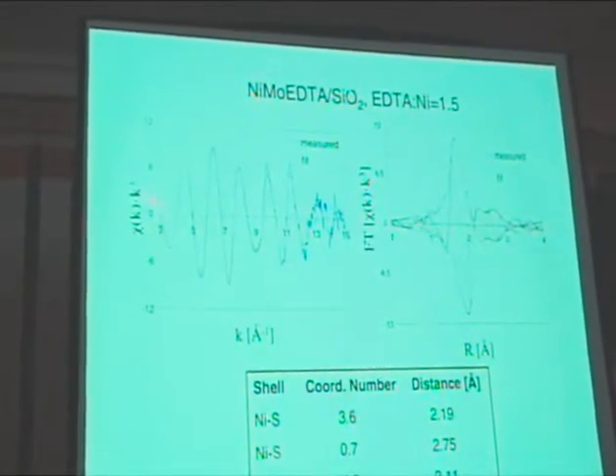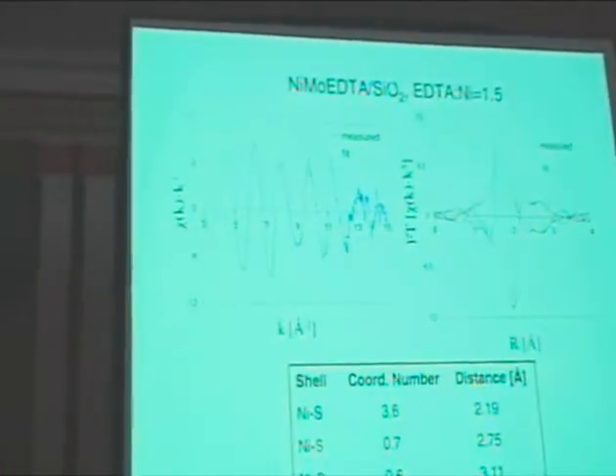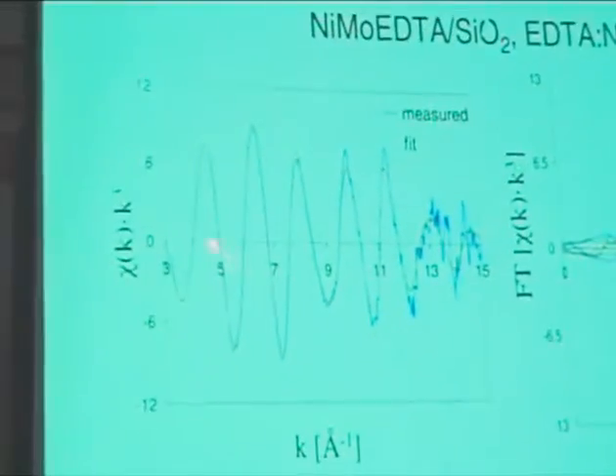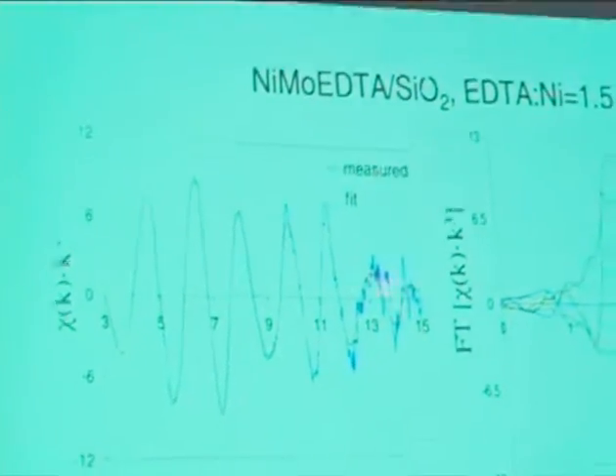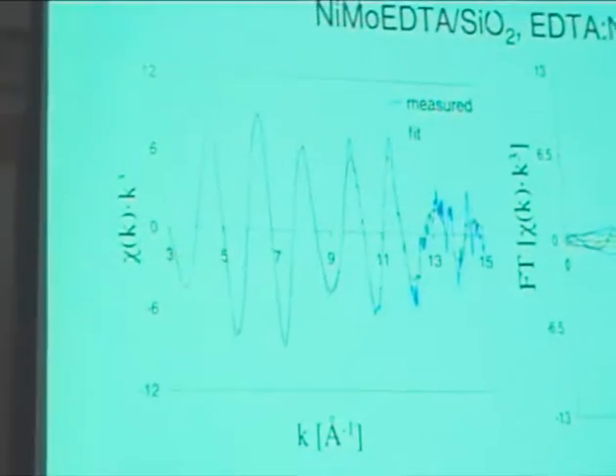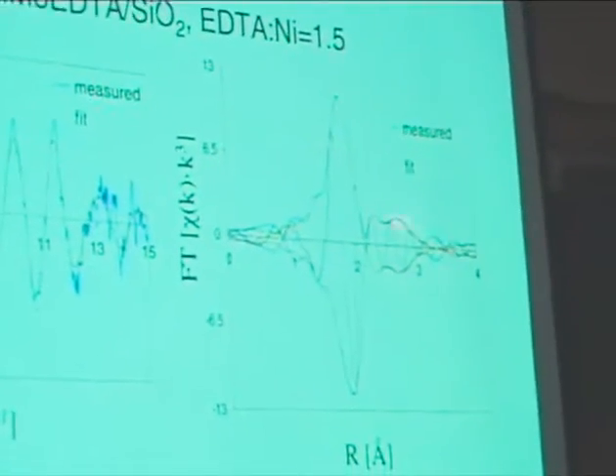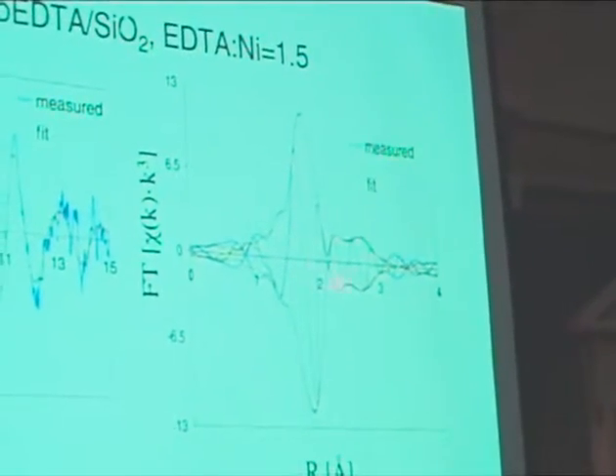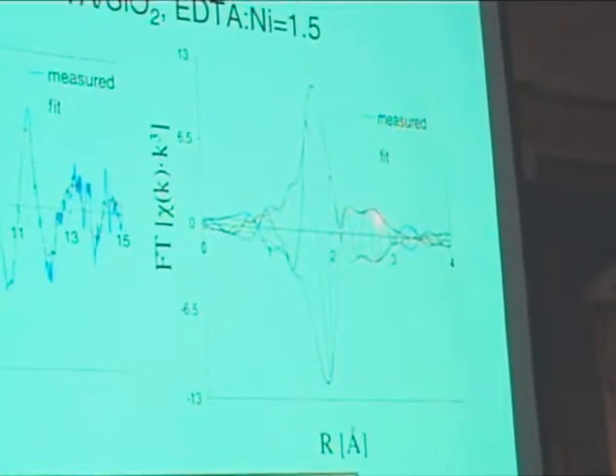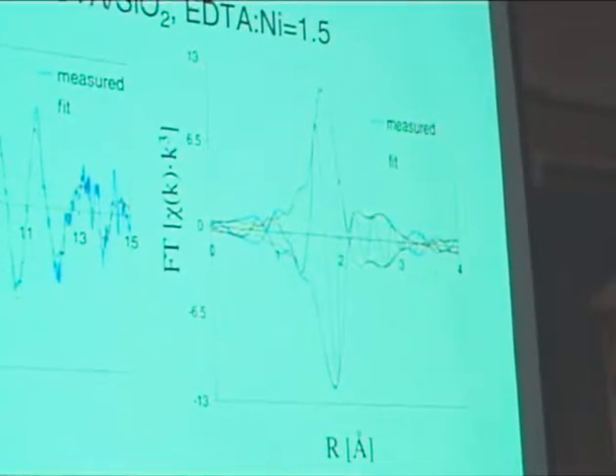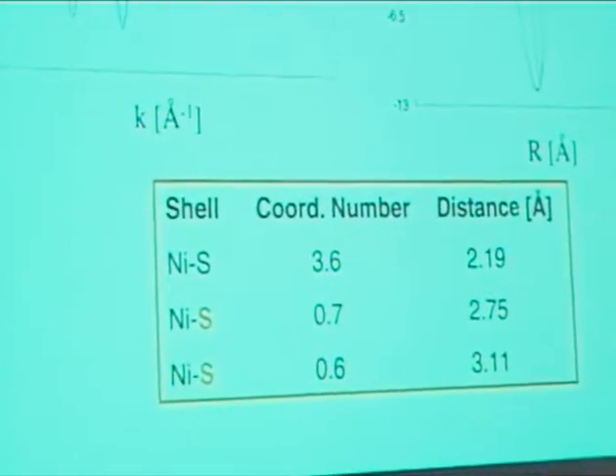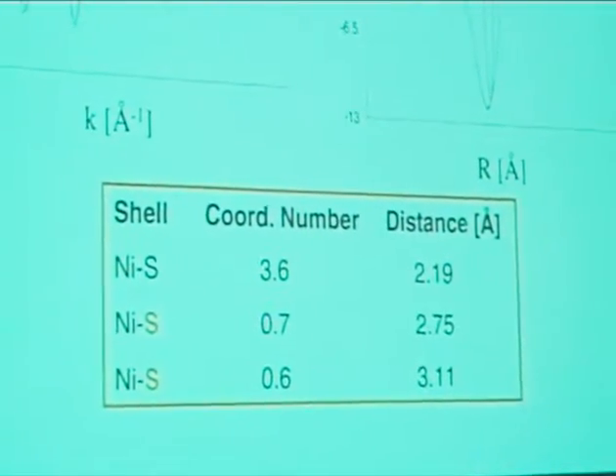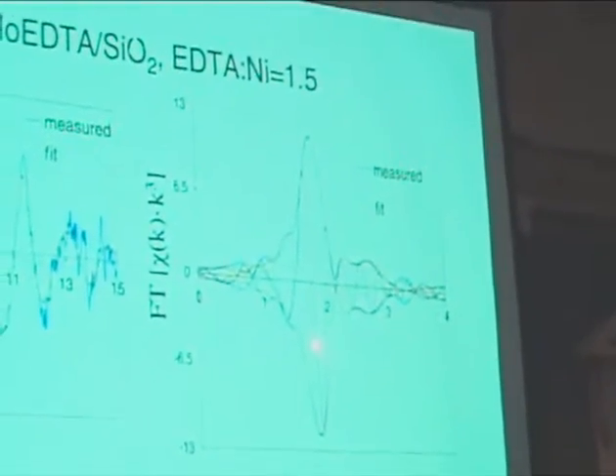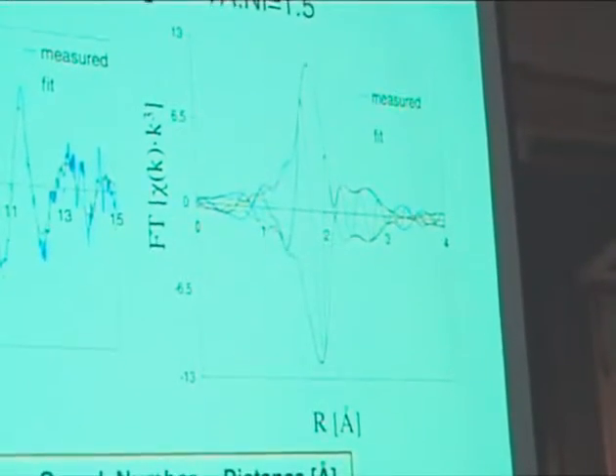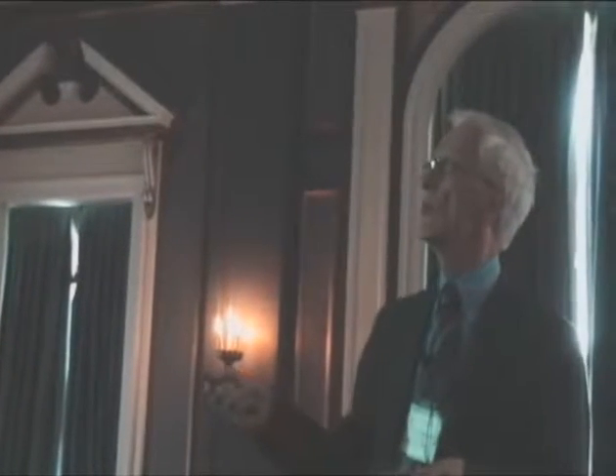I can also do a k to the power 3 transformation. Now I'm a little bit technical, but this is a trick to multiply the region at high k, which then after Fourier transformation is at high r. So now you see that the spectrum is different, but now definitely I have 1, 2 peaks here, and I have my main peak. And what I now can do, I can use my formula to fit those peaks. And if I do that well with the right model compounds or with the right theoretical fitting models, I can tell you what this peak is.